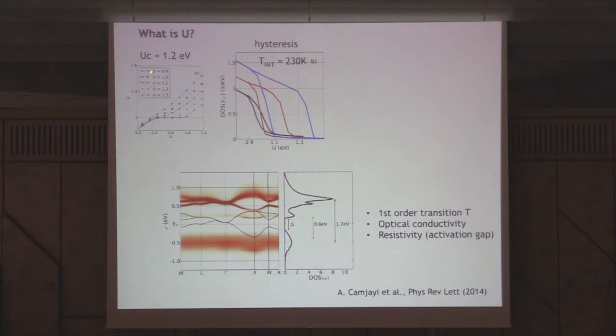And when we open the gap, we said, well, U has to be right there. So we fixed, of course, in the experiment, you do something a bit different. You fix the value of U, and you change the bandwidth. But since the changes are small, it is just more practical to have one band structure calculation and then use U as a parameter. So this is what we've done. We fix the band structure, and we use U as the parameter.